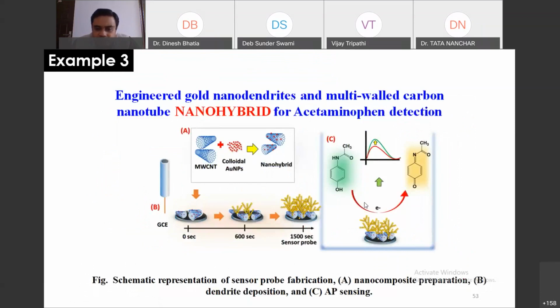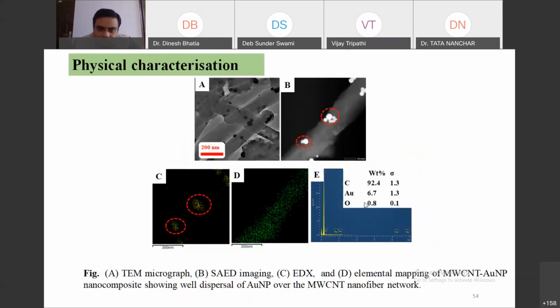We have developed a nanohybrid in the very first case where gold nanoparticles and multi-walled carbon nanotubes had been utilized, and then this was used as a surface where a dendrite has been grown. Right, you can see first what we have done. We have prepared the gold nanoparticle and the nanotube. You can see all this data here: SEM imaging, EDX, and mapping. Also, you can see the presence of carbon and gold in the whole system.